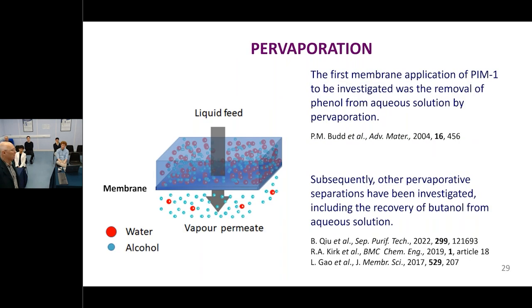But we've been focusing, in our research, very much on membrane applications. And I mentioned pervaporation earlier, and this was actually the first membrane process that we looked at, simply because I've been looking at pervaporation with zeolite membranes when this came along. Pervaporation is a process where, with most polymers and most other materials, if you put them into a membrane, if you have an aqueous mixture, it's the water which transports preferentially. And that is used at present. It's used both with certain polymer membranes like polyvinyl alcohol and also certain ceramic membranes. And you know, zeolite is really good at it.